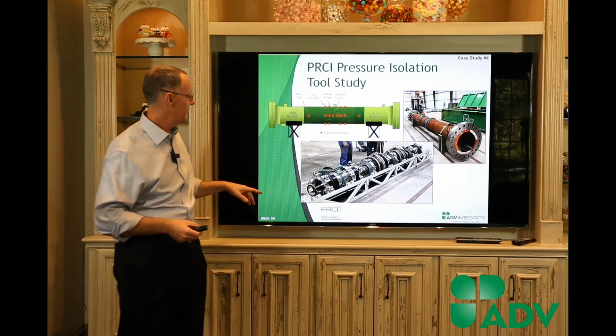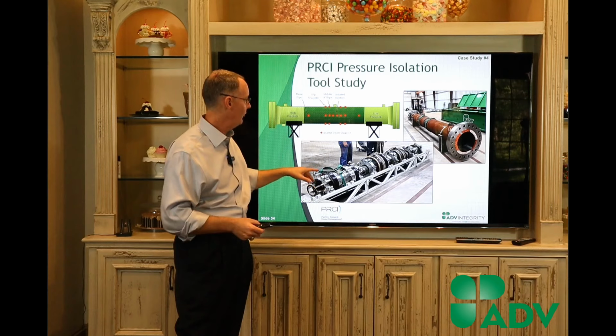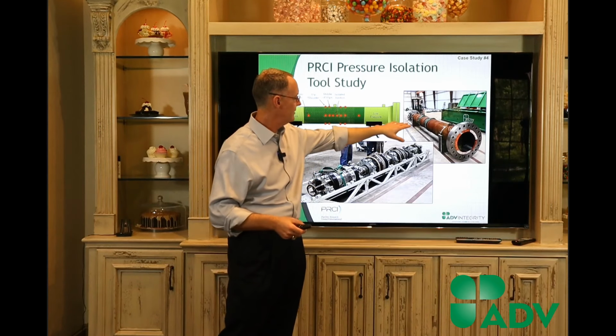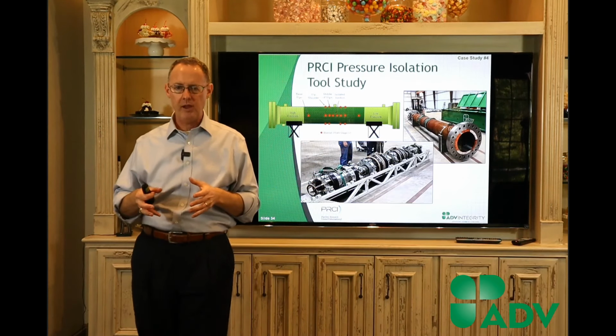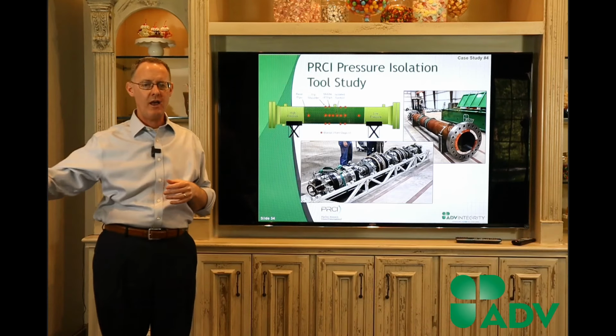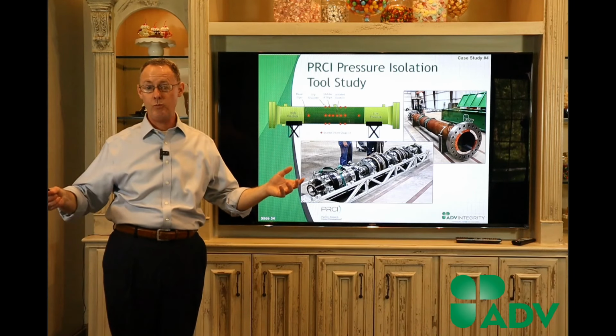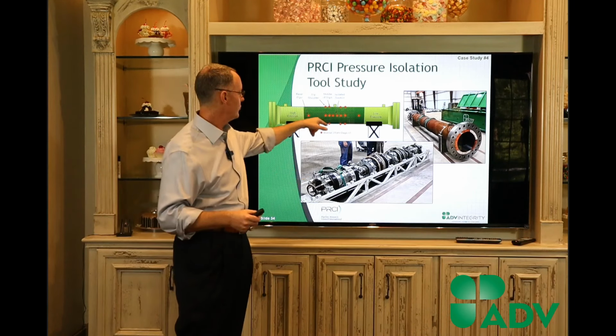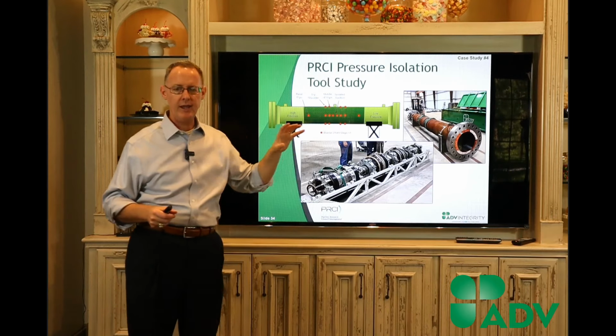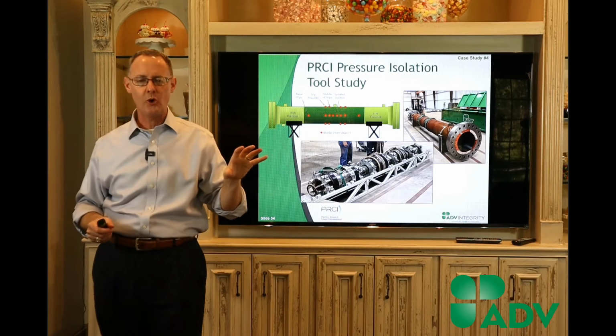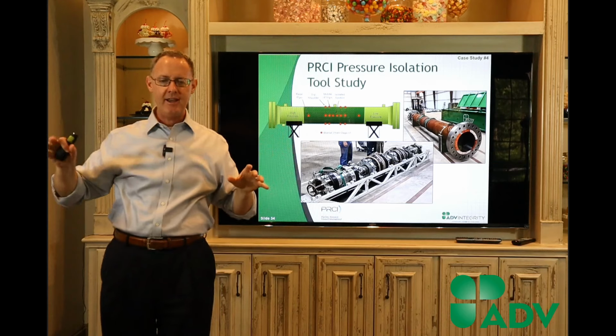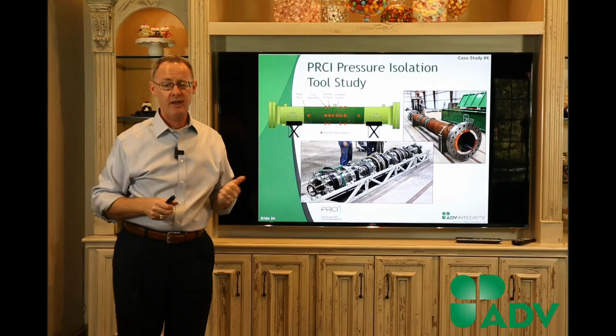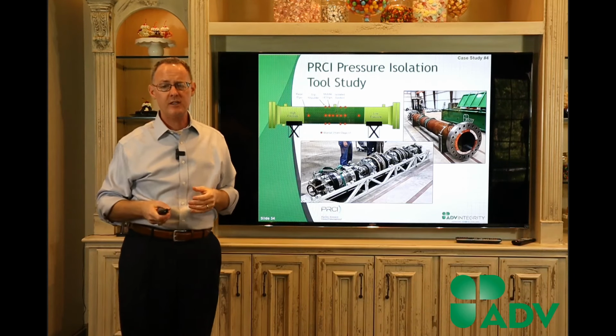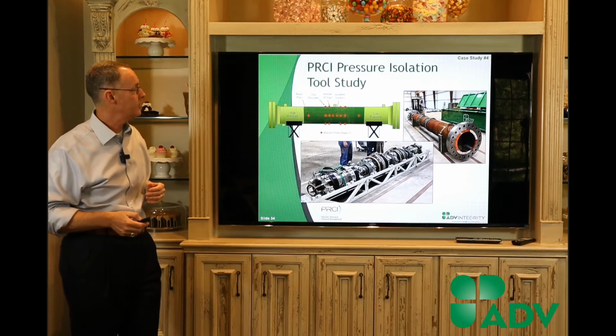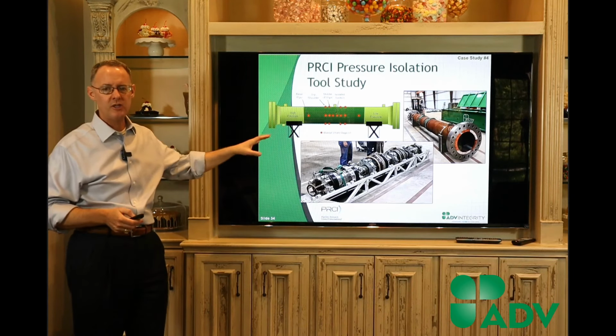And so this is one of the isolation tools. So we drop it in our little test fixture. It locks in place. We pressurize one side, and on the other side, we don't want to see pressure. And you can see we're putting a lot of strain gauges on and we're measuring it. And if you remember the image I showed earlier that had a lot of crazy data, this was actually from that project. And so we went through, we processed, and we determined what the stresses were. So just a great example of how you can use analysis and testing.